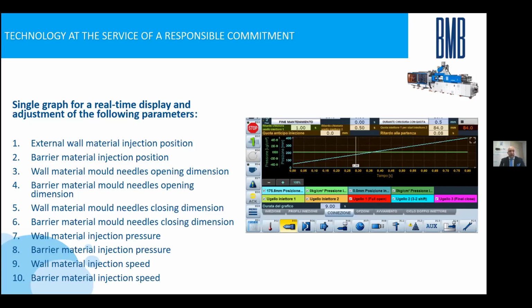article is that we have to control the hot runner, very high quality hot runner of the mold, with three sections of the hot runner. We open totally the hot runner, and we start with the first material, external material. After we close 50% the hot runner, and we start with high-speed injection with the second material. This is the layer inside in PVOH, we will explain. And after, we will restart with the same material of before.